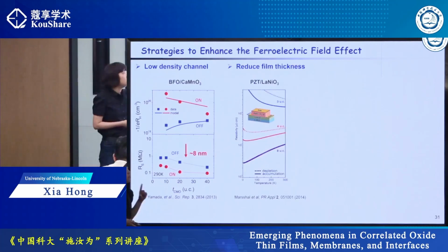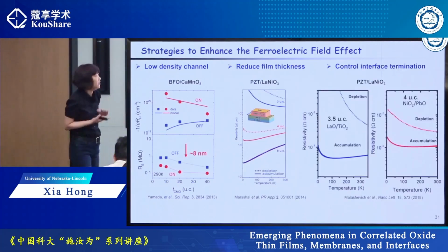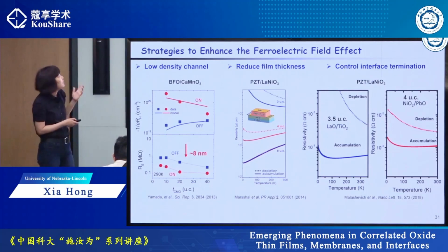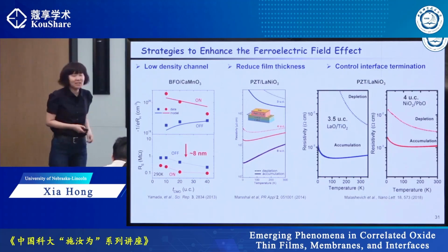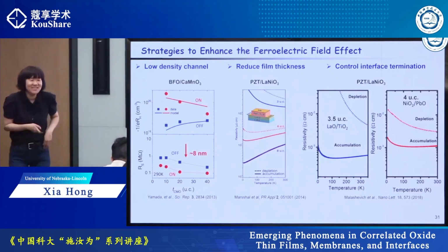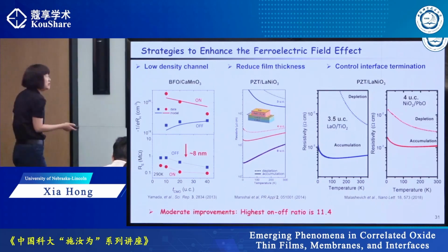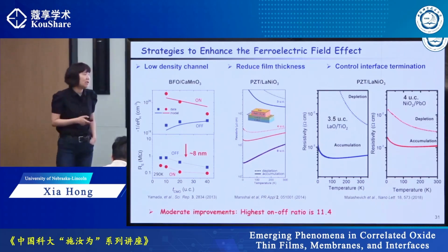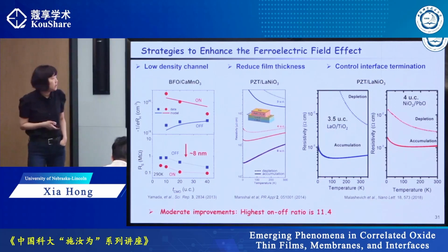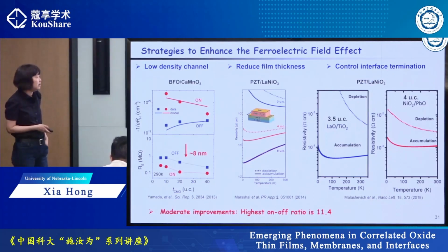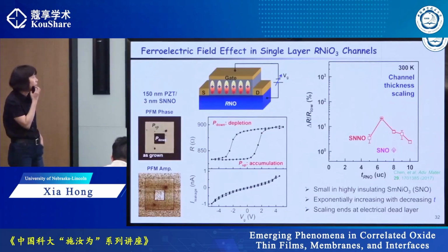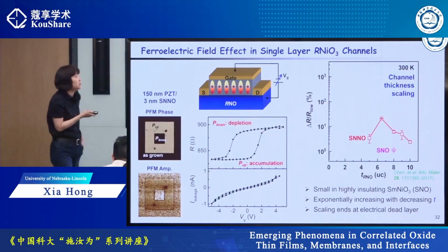Another approach is to reduce the film thickness. This approach has been intensively investigated by my PhD advisor, Charles Ahn's group, with not much success. The highest on-off ratio they have achieved is around 11.4. We observe a similar effect.